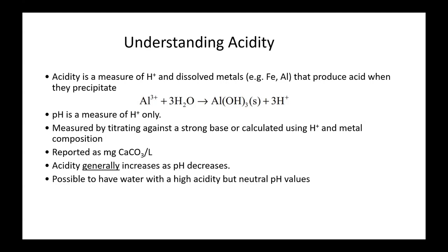So it's generally reported as milligrams calcium carbonate per liter. It generally increases as pH decreases. So as the pH gets more acidic, obviously the water has more acidity. But you can have water with high acidity but neutral pH if it's got a lot of dissolved metals in it of particular types that are still soluble at neutral pH. So it's just an indication that acid rock drainage can generate a lot more acid than you might think just by looking at its pH.